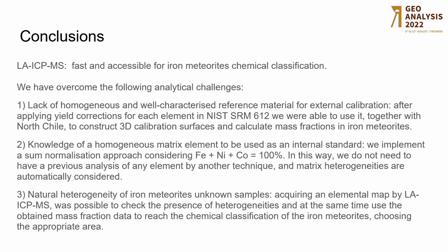The second is the need for knowledge of a homogeneous matrix element to be used as an internal standard. Then we implemented a sum normalization approach, considering iron plus nickel plus cobalt equals 100%. In this way, we do not need to have a previous analysis of any elements by another technique, and matrix heterogeneities are